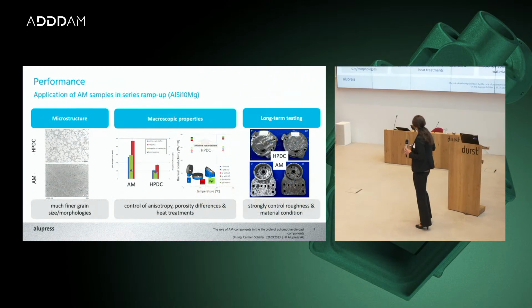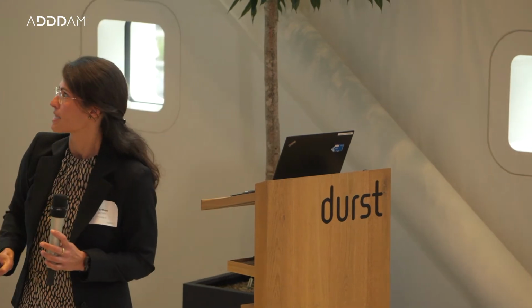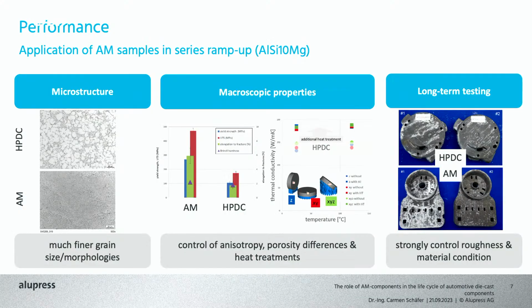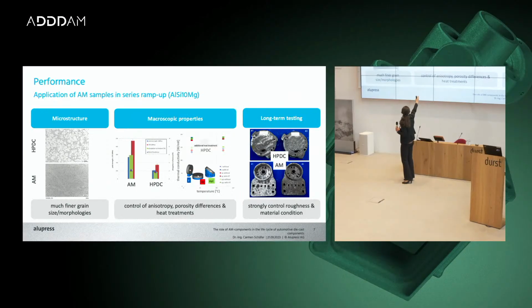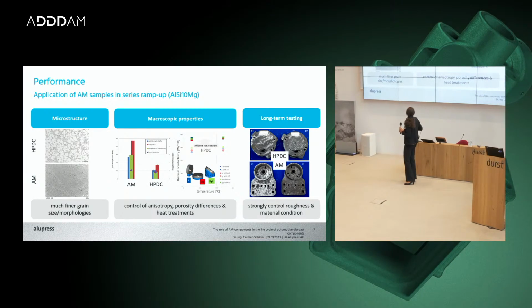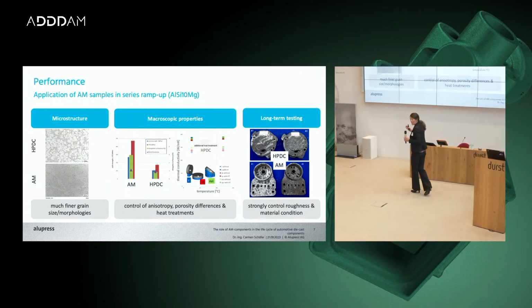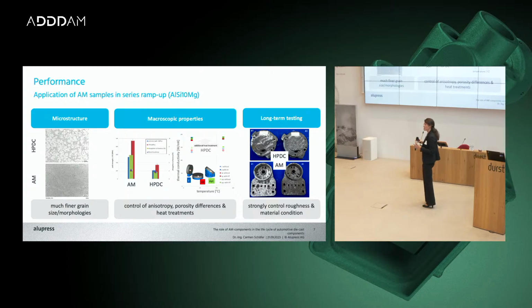Before I come to the next part, for series production, there is one issue to discuss about AM and die casting. You see it on the first slide, it's the microstructure. High pressure die casting has a fast solidification rate, but AM is even a factor 100 faster. Very fine microstructures, and they result in excellent properties. You have the high pressure die cast, and you have on the left hand side the AM properties. They are anisotropic, you need to consider that. It's not a showstopper, but you need to keep it in mind.